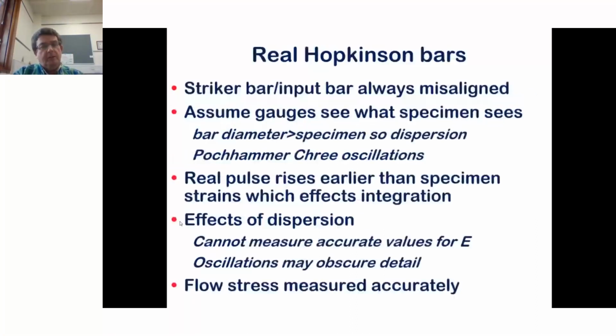Well, we can never perfectly align bars. We assume that the gauge sees what the specimen sees. More or less, that's correct. We assume we know when pulses rise. That's another assumption we're making, so that we can align transmitted and reflected pulses in terms of time of behavior at the sample. Those gauges are remote from the sample. We have to move the time basis to say what we believe is happening at the sample. And we got dispersion as well.